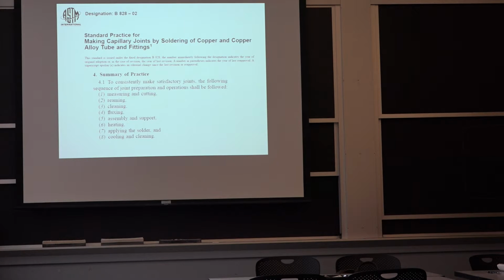Okay, so it is literally a weld then, basically. Well, okay, it's not fusion welding because you clean the copper, and you bring a liquid metal into the joint by capillarity. So it gets drawn because it's a very confined space. So you're reducing the amount of free surfaces, and it only works if you're really replacing two metal interfaces with just one. But if you're trying to put the metal on an oxide, it doesn't reduce the energy, so it doesn't want to do it.